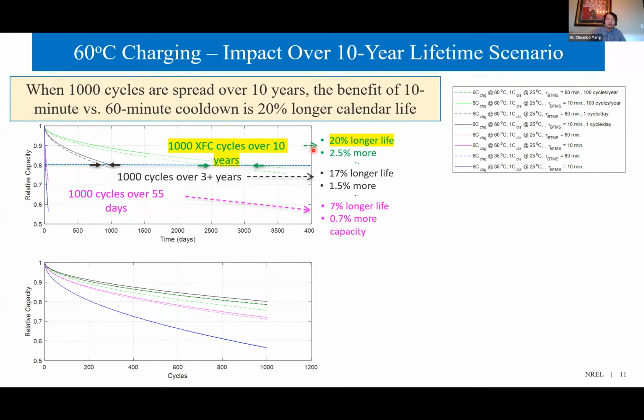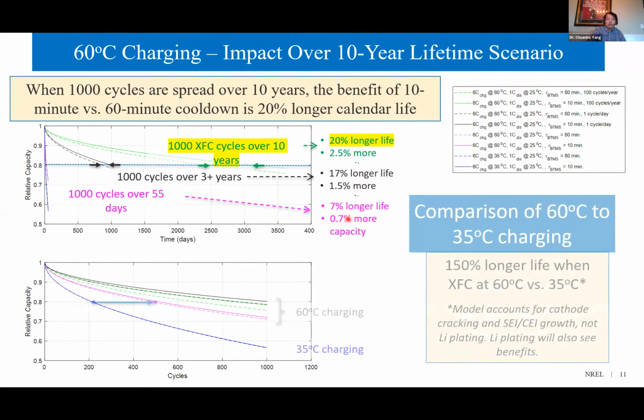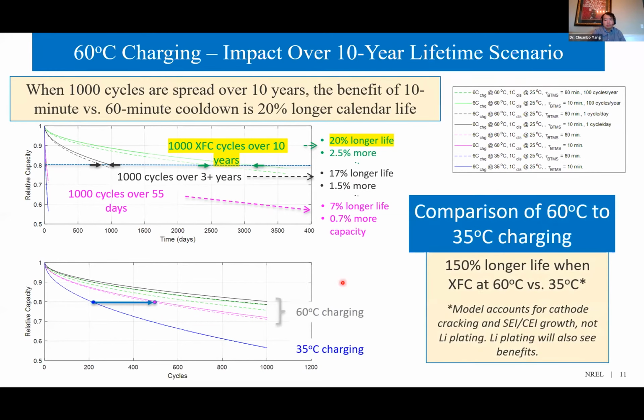The trade-off is the cost of a larger battery thermal management system versus a 2.5% larger battery to account for extra fade. This will decrease if the fast charger is used more often, such as 1,000 cycles over 3 years. The benefit will be 17% longer life. Except for the cooling time constant, other scenarios will directly address fast charging at a high temperature.